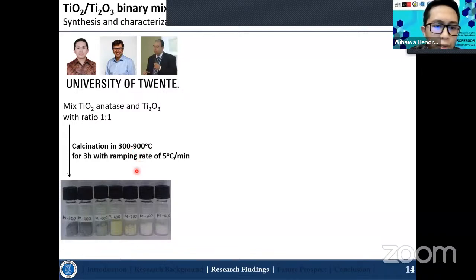And it is actually very interesting, where we can see the changing of the colors by increasing the temperatures of the calcinations from 300 until 900. The colors gradually changed from gray, light gray, and interestingly at 600 degrees it forms a yellowish color. And at higher temperature, at 700 until 900, it forms the white color.